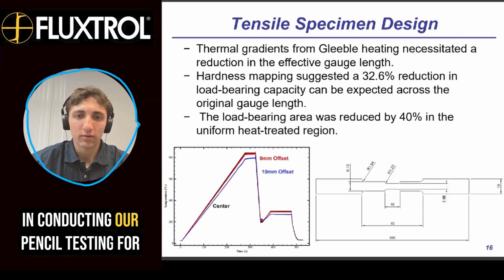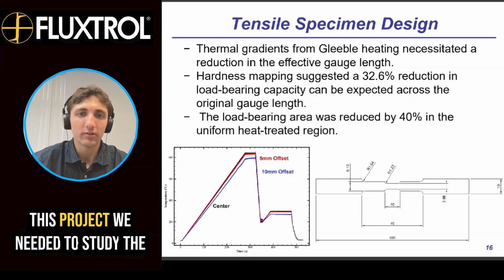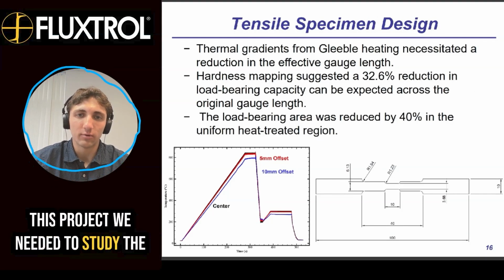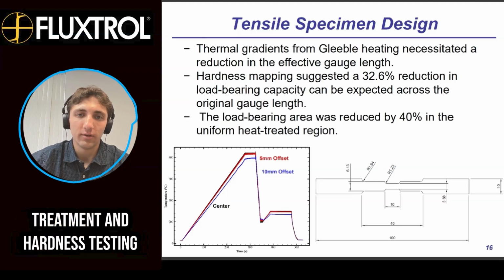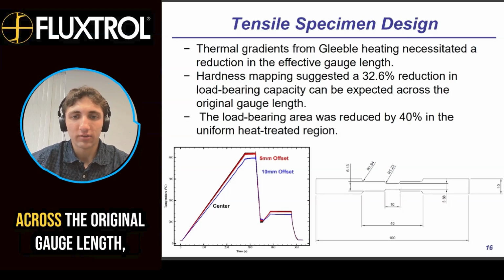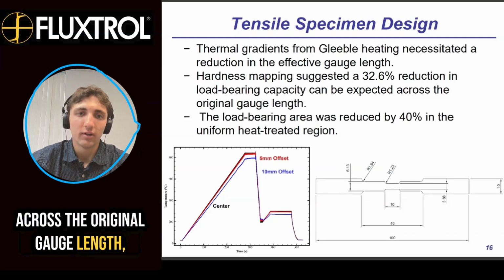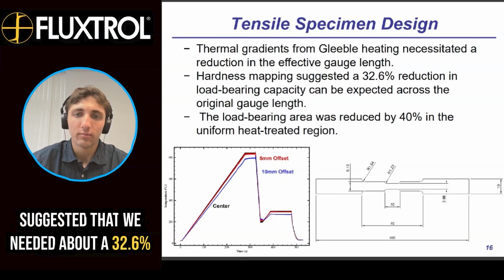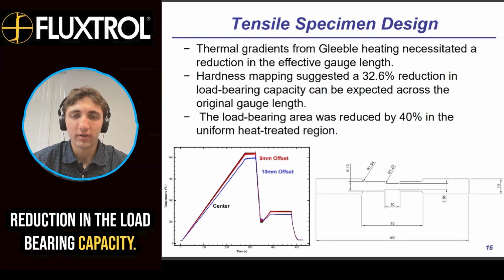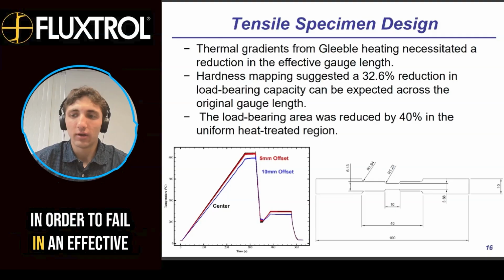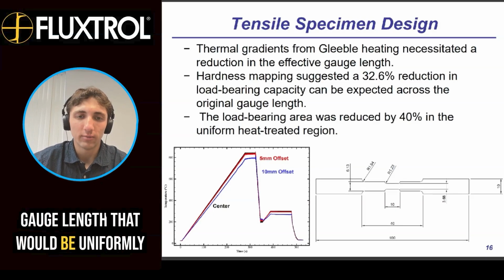In conducting our tensile testing for this project, we needed to study the thermal gradients from Gleeble heat treatment, and hardness testing across the original gauge length suggested that we needed about a 32.6% reduction in the load-bearing capacity in order to fail in an effective gauge length that would be uniformly heat treated.